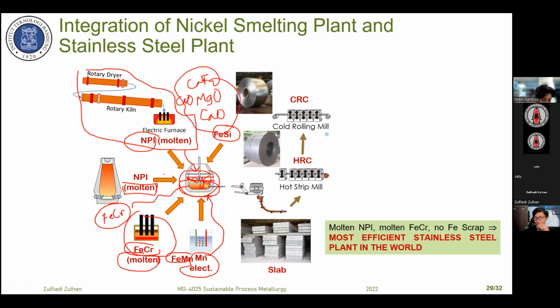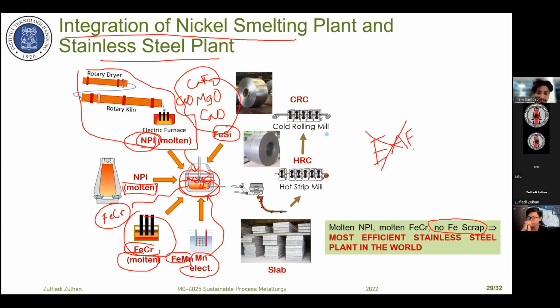But we see from this kind of combination, because of the integration between nickel smelting and the stainless steel plant, we can use the iron from NPI. We do not need any iron scrap. So this kind of route is actually the most efficient stainless steel plant in the world. Actually, we do not need any energy for melting in the EAF. No EAF required. The CAPEX is lower, and the OPEX is also lower compared to conventional stainless steel making.